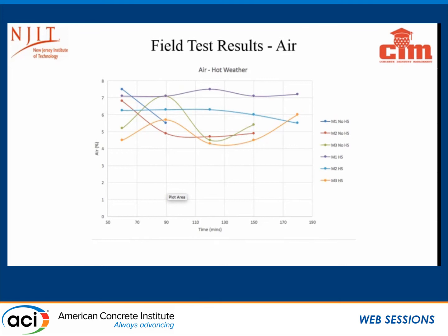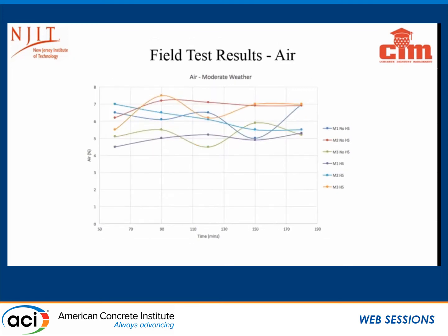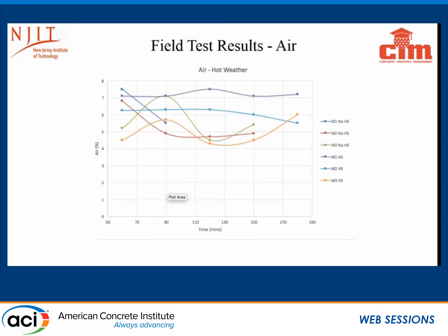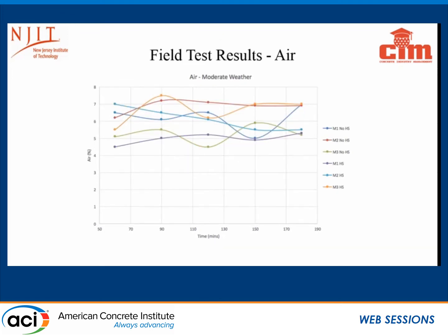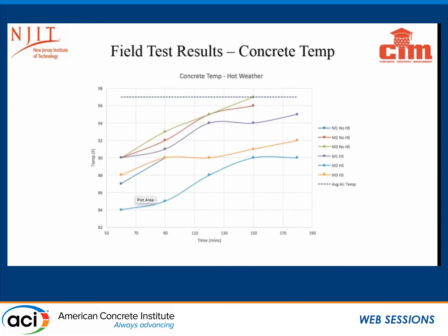So it's continued proof that utilizing admixtures is pretty much what's going to guarantee or assist you in achieving these results. Right? Air entrainment, during moderate weather, is even more consistent when you compare to some of the mixes. It is a little erratic during hot weather, but in moderate weather, it's more stable. Temperature. This one is the hot weather graph. The average air temperature in August was about 97 degrees.